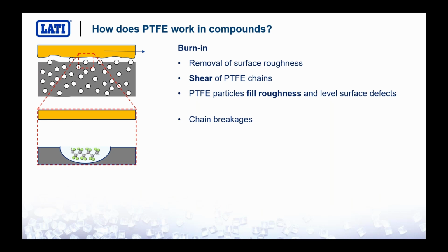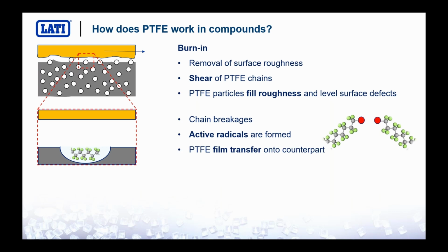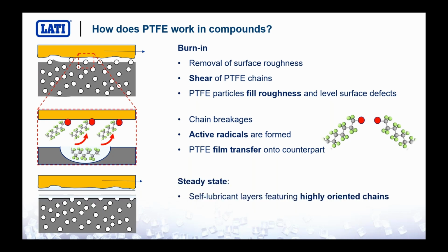What happens when you break the chain of a polymer? You create radicals. You create radicals which are extremely active chemical species, which are prone to react very quickly, and these chemical species will react with the orange part. This means that the PTFE radicals will stick onto the orange surface, promoting the so-called film transfer. So you will have PTFE not only on the surface of the gray part, but also on the surface of the orange part. So you will have PTFE on PTFE with extremely oriented chains.